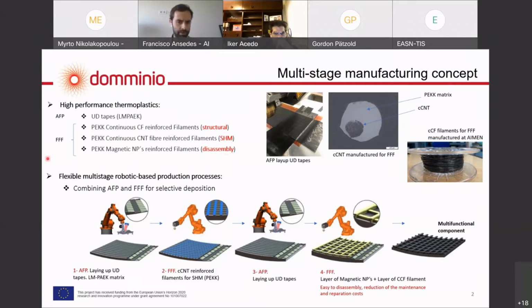So going into the multi-stage process, in this case we are using a multi-stage robotic-based production because both the AFP and FFF are robotized technologies that are mounted on robotic arms, and in the DOMMINIO process we alternate between the two stages. We laminate and lay up the UD tapes with LM-PAEK matrix to be the structural monolithic skin of the parts, the panels, and we will lay up with AFP.